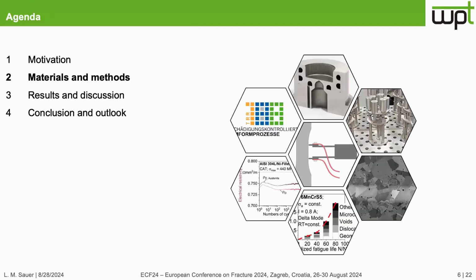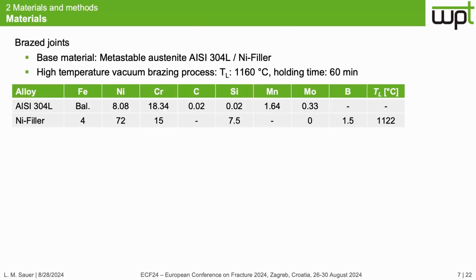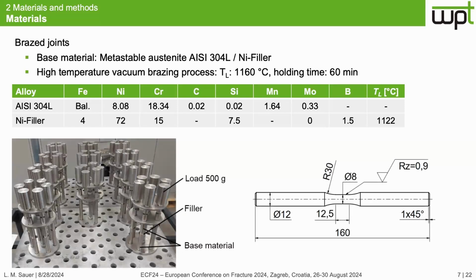I will now come to the material and methods. The used material were brazed joints with a metastable austenite AISI 304L and a nickel filler. The used brazing process was the high-temperature vacuum brazing with a temperature of 1160 degrees and a holding time of 60 minutes. And after the brazing process, this shown fatigue specimen was produced.